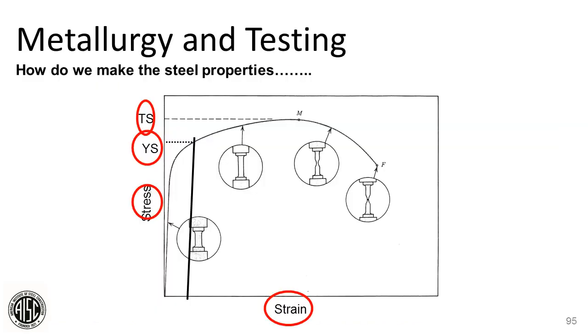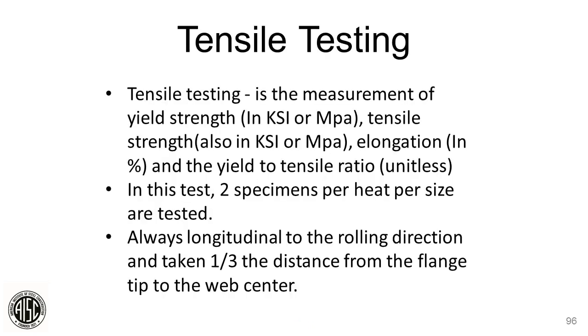Next slide. Now this you're all familiar with. This is your stress strain curve, and the yield strength is the point that you see on your test report that you do all your designs on and so forth. I know I don't need to spend a lot of time on this. It's more of an introductory slide for what we're going to talk about next. So next slide. Tensile testing. Again, two test specimens are taken per heat. That is the ASTM specification. ASTM also calls for shapes to always be tested in the longitudinal direction, one-third of the distance from the flange tip to the web center. Next slide.